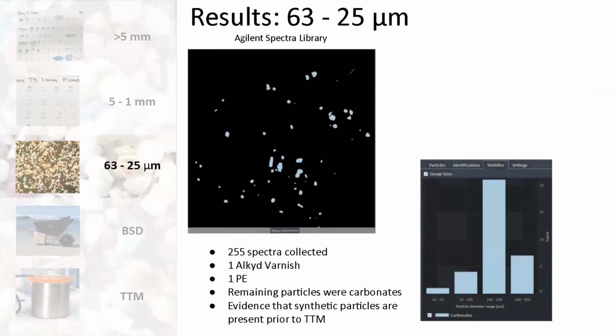For the sand that we sampled and sent out to them, there's 255 spectra collected. Of all of the sand that they analyzed, there were only 2 synthetic polymers found, an alkyd varnish and polyethylene. Everything else was carbonates. So very good results from the buoyancy separator device, removing this material from the sand.